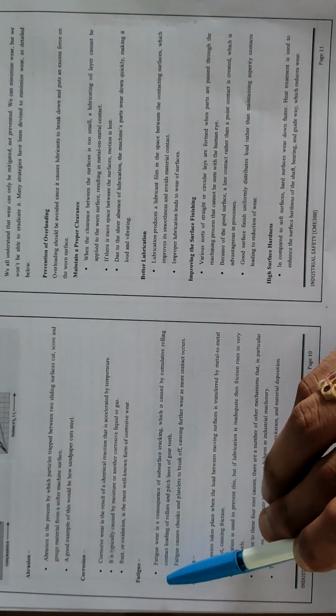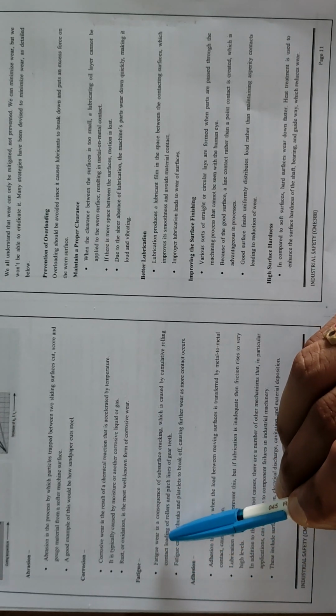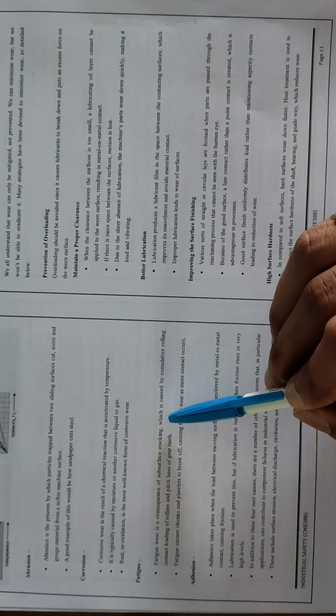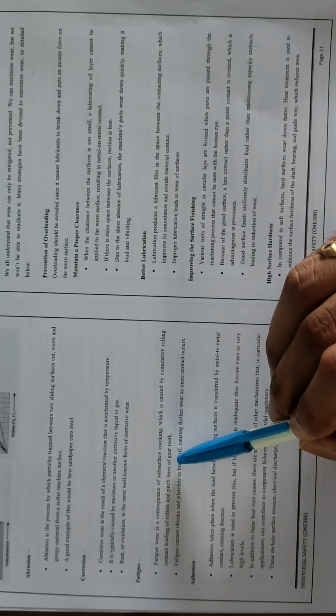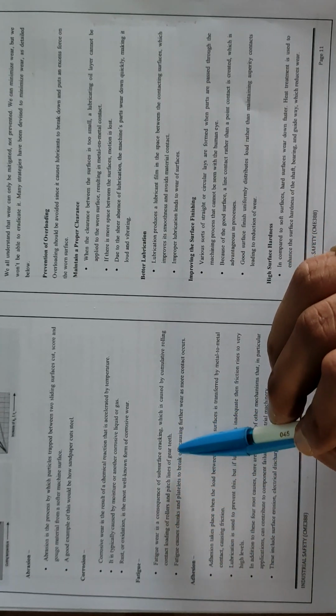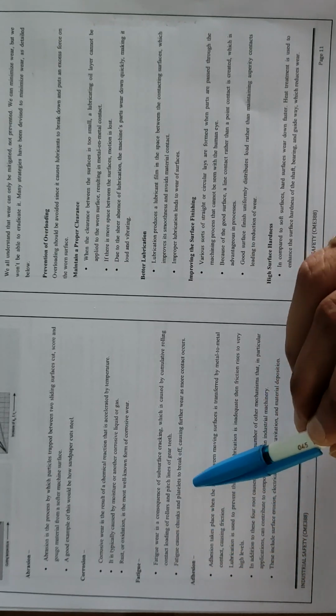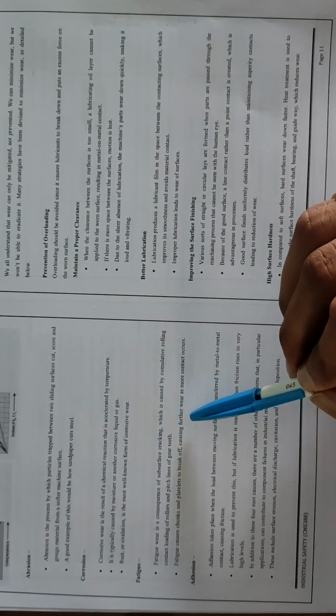Fatigue wear is a consequence of subsurface cracking, which is caused by cumulative rolling contact loading of rollers and pitch lines of gear teeth. Fatigue causes chunks and platelets to break off, causing further wear as more contact occurs.